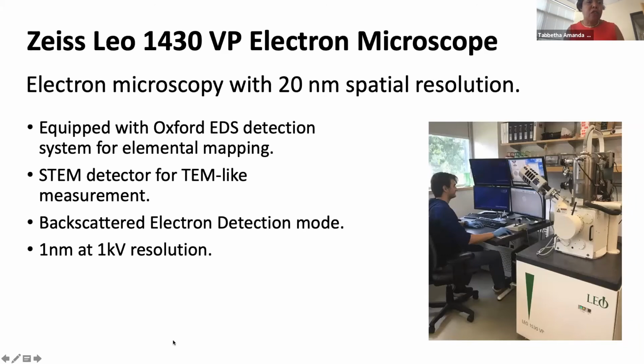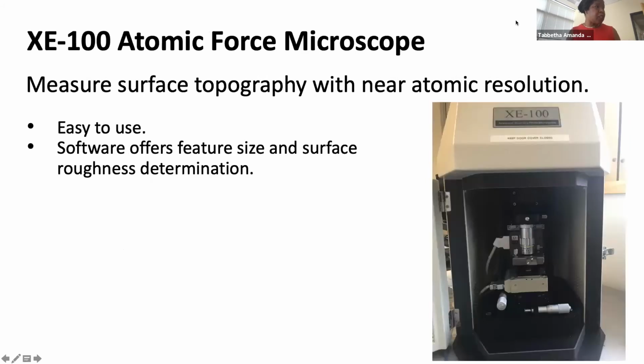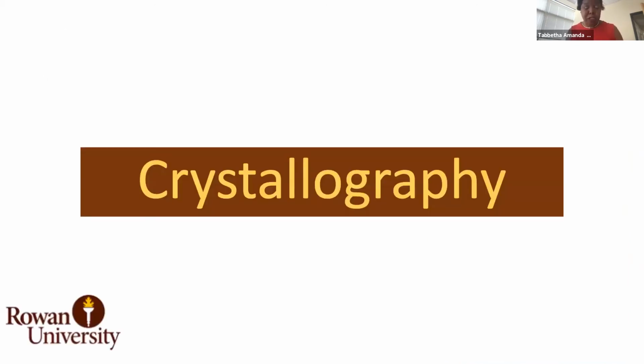Our older electron microscope is the Zeiss Leo electron microscope, and it has around 20 nanometer spatial resolution routinely. And again, we have installed the Oxford detector onto that microscope so that you also are able to get the elemental maps and be able to see the exact chemical analysis. And then finally, under the microscopy suite, we move from electron microscopy to atomic force microscopy. This is a scanning probe technique where you're able to actually scan the tip over the surface of your sample to topographically see near atomic resolution of your sample surface. And so these are the microscopy instruments that we have available.